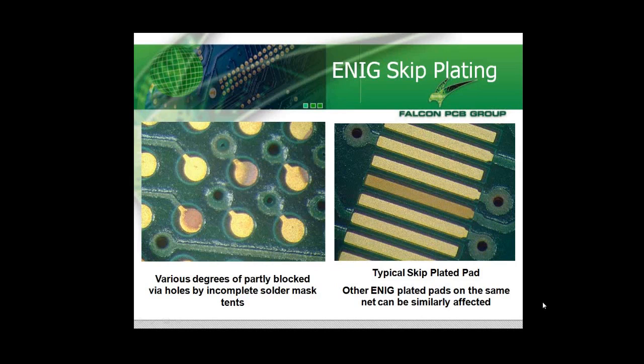Depending upon the drilled hole sizes, not all the actual solder mask will tent fully all areas. And as you'll probably notice, there are variations on each one of the residual solder mask. In particular, the one I'm indicating with the arrow at the moment is absolutely classical of what will cause you skip plating. As you probably notice, exactly what Nigel said, every pad that's attached to that via hole on that same net will almost certainly be affected in the same way.